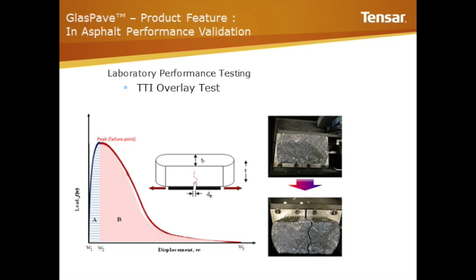So with that being said, what the test does is it applies a load, if you look at the graph here, and eventually it reaches a peak displacement. The asphalt at that point does not necessarily fracture. If you go back to those other test results that I showed you earlier, you may not necessarily see a crack at that point, but it's a point at which you've exceeded the strain capacity of that material. And then it shoots off and you lose significant tensile serviceability.